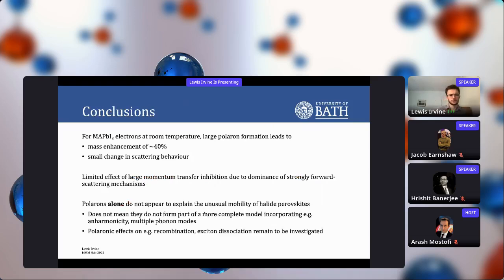So to conclude, to wrap things up, for MAPI electrons at room temperature, large polaron formation gives a mass enhancement of about 40% at room temperature, and a small change in the scattering behavior. There is an inhibition of large momentum transfer scattering events, but because the dominant scattering mechanisms in halide perovskites are already strongly forward scattering, this has a limited effect.